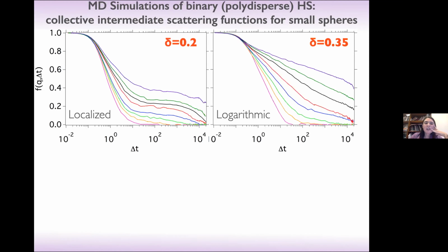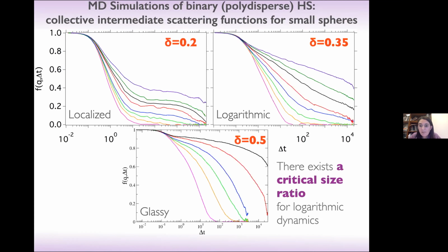So we did binary polydisperse hard spheres, and we measured the collective intermediate scattering function of the small spheres. You see that I report similar size ratios to the experiment, 0.2 and 0.35, and that the phenomenology is really the same. We have this localization transition here, and we have this logarithmic behavior here. Then, of course, in simulation, you can also do delta 0.1, 0.3, 0.4, 0.5, everything. In the experiments, it's usually more difficult.